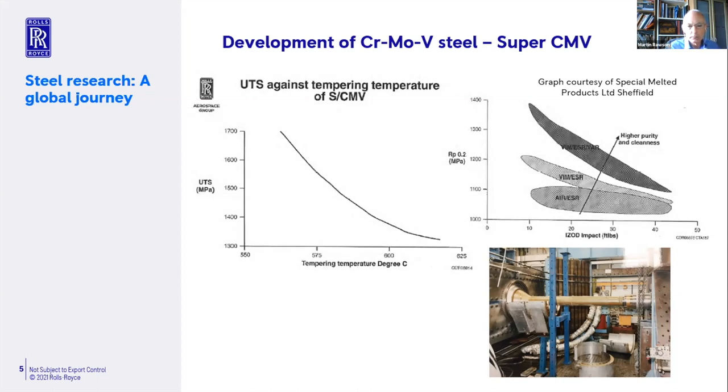It's easy enough metallurgically — all you need to do is reduce the tempering temperature. But if you reduce the tempering temperature, you increase the UTS while getting reduced toughness or reduced impact resistance. There has to be a balance as to how much you can afford to increase the UTS and lose toughness. In a safety-critical industry like aero gas turbines, there's a lot of conservatism, understandably, because making big changes is bold. Hence why we have the Materials Structural Advisory Board — to consult with the best in the world to make sure decisions are sound.